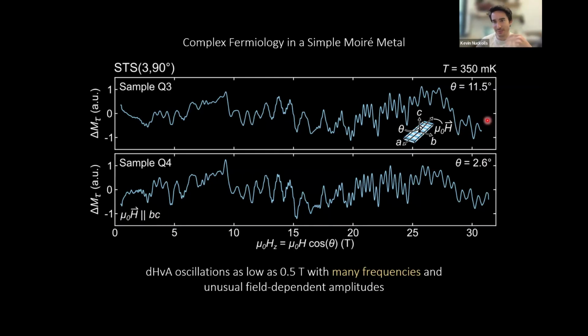If you did quantum oscillation studies on something more typical like graphene, then you would find that a small quantum oscillation at low fields would become a very large quantum oscillation at higher fields. And that's not what we're seeing here, because there are actually many frequencies represented in this Fourier transform. These many separate frequencies are destructively and constructively interfering to create this rather constant amplitude magnetic signal that we see at all magnetic fields. So Onsager would again implore us to make this statement more quantitative and to Fourier transform these.